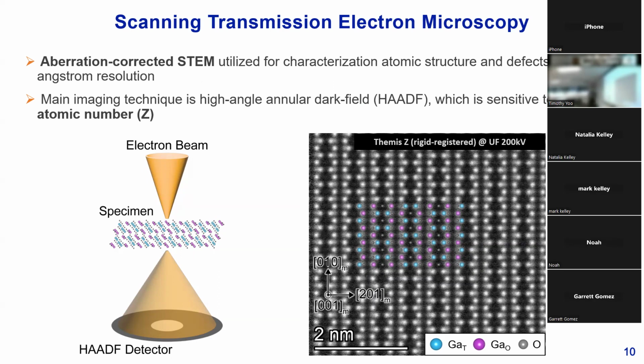How it works is you have a strongly focused probe of your electron beam here. It's rastered across the surface of your sample rapidly. And as these electrons are transmitted through, electrons that are scattered at particularly high angles are going to be captured by something called your high angle annular dark field detector. The signal from these electrons is going to be proportional to the atomic number Z. So in this example image on the right of 001 oriented beta gallium oxide, the bright atomic columns, these bright spots here in the image, are going to be your gallium because they're relatively higher in atomic weight than the rest. And the oxygen in this case, in gray there, is going to be so light that you actually can't see it.